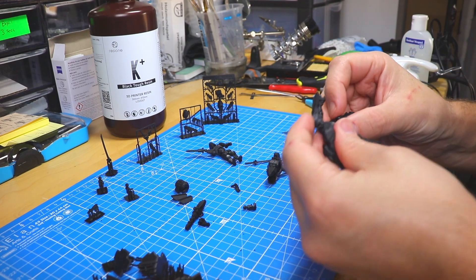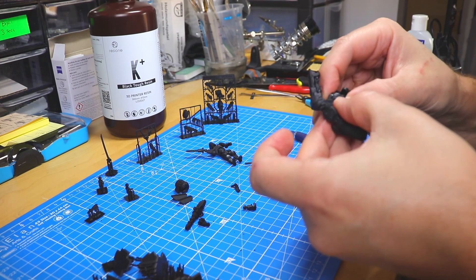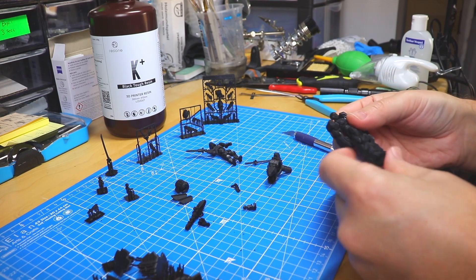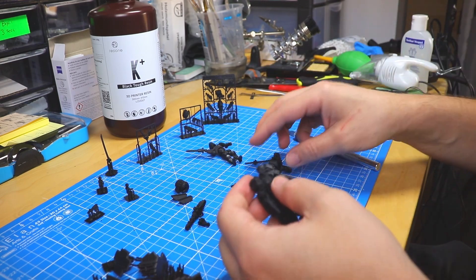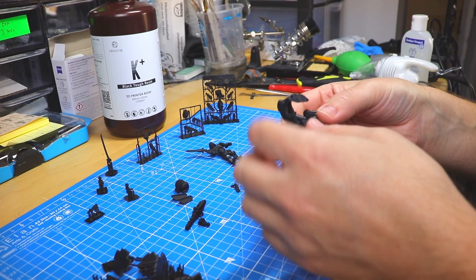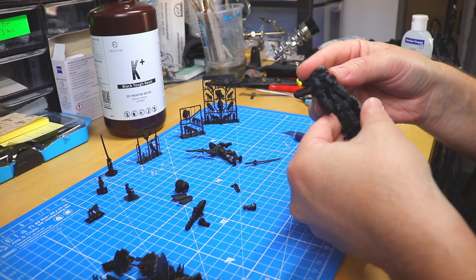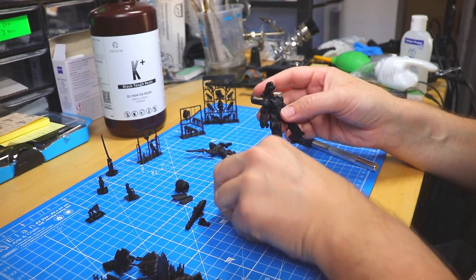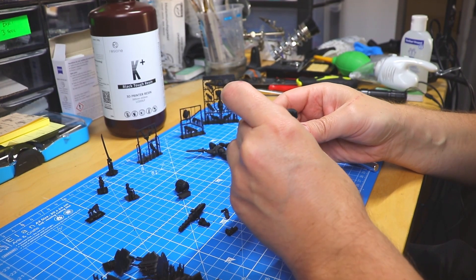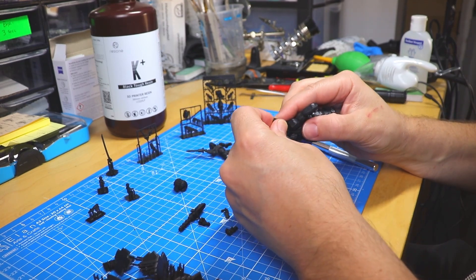The only downside with the action figures is that if you print at a lower layer exposure, you have perfect fits for the parts — the tolerances are all perfect. But for real nice joints, you need some grip, and you actually need a higher exposure setting. Some resins also tend to shrink over time and you never know how they exactly behave — you have to test this. For action figures, it's always better to print at a higher layer exposure setting. It takes some experimentation to find your favorite resin and the right settings — it's not rocket science, but it takes some time.